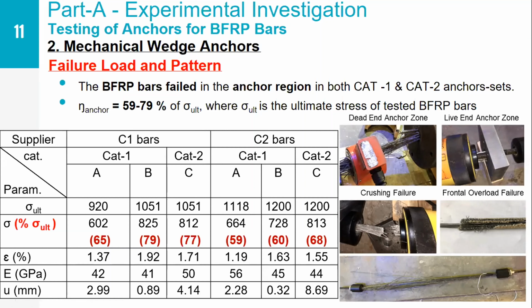However, the ACI guidelines for using FRP bars for prestressing application recommend that an initial prestress of 50% of the ultimate strength has to be applied. So since these anchor efficiencies are above 50%, these anchors can still be used. However, we are still conducting further research in our group to see if the efficiency of these industrial wedge anchors for prestressing BFRP bars can be further improved.